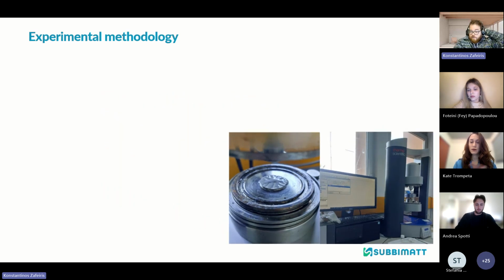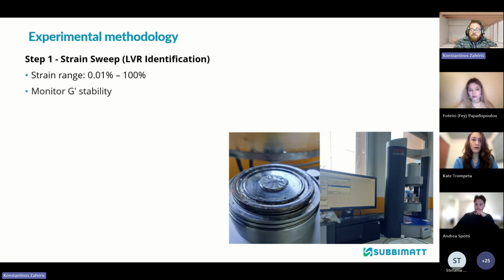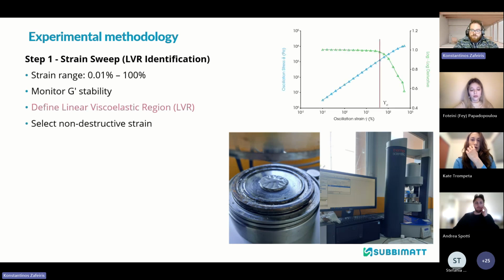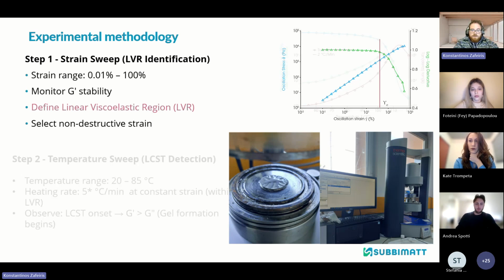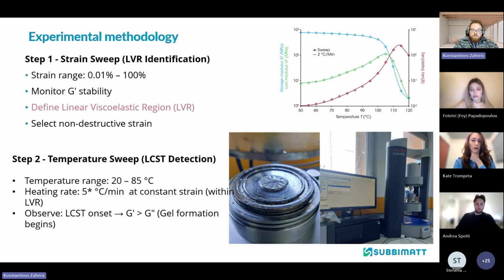Our experimental approach is based on oscillatory rheology. What we did first was to perform what we call strain sweep tests in order to define the linear viscoelastic region. This is the range of low deformation where a material's viscoelastic properties, for example the storage modulus, are independent of the applied force, thus ensuring a linear relationship between stress and strain. After that, we perform a temperature ramp test while varying the heating rate, under low deformation of course, to remain within the linear viscoelastic region.